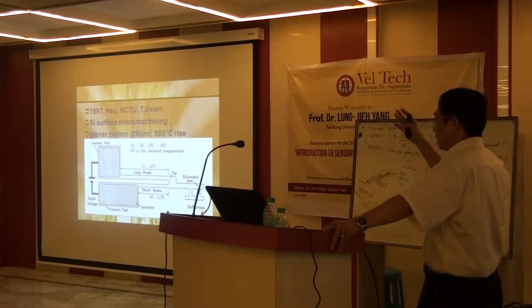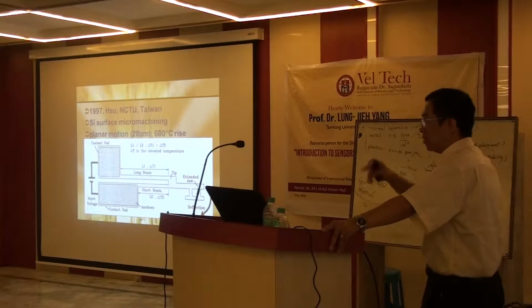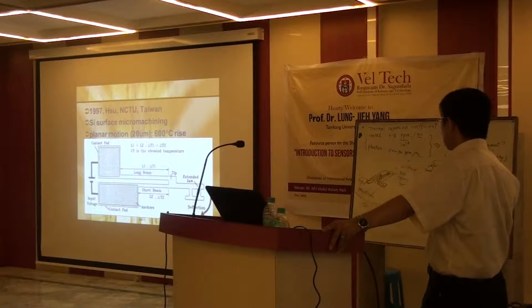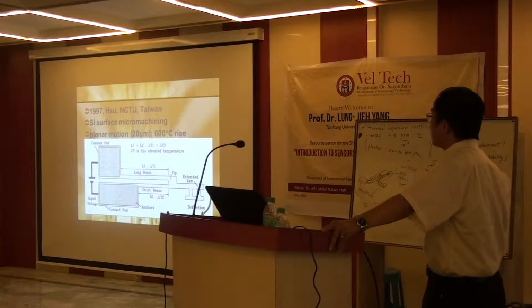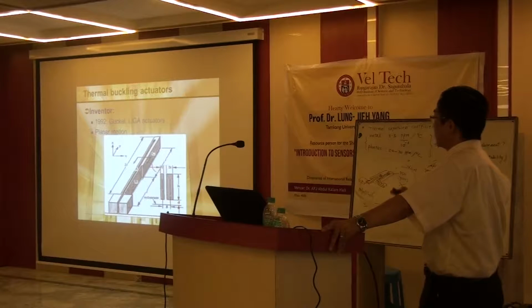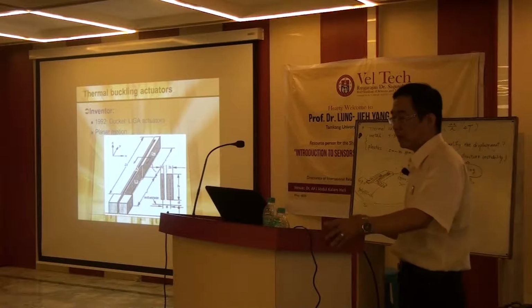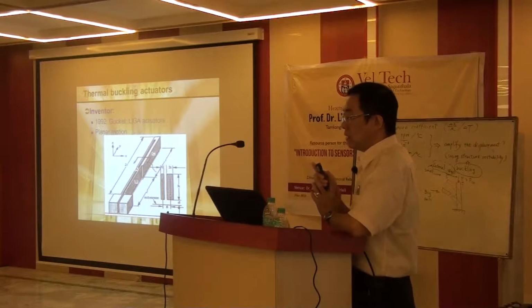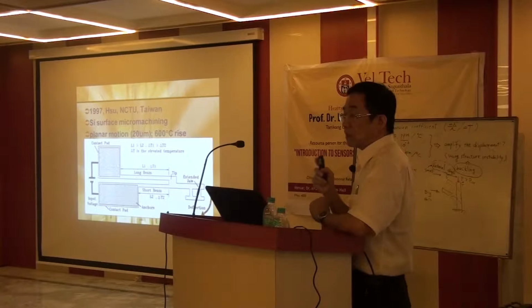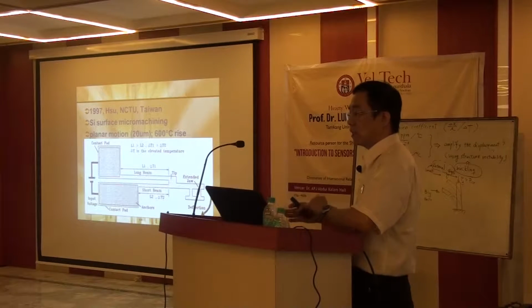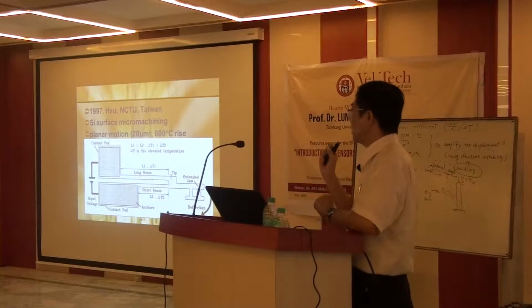Two sets of thin coating, photolithography, and etching. And you can finish the geometry, the patterning. Okay, so here's a planar motion about this arrow, about 20 micrometers. The temperature increase is about 600 degrees C, comparable to the results of Professor Gakko in 1992. But the one advantage is no more using the LIGA process. We use the ordinary clean room and surface micromachining. We can finish this kind of process.